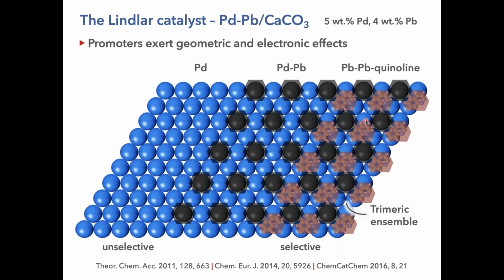Now, with this understanding of very well-defined motifs, in this case a trimeric ensemble of palladium, the design of better catalysts, that means containing much less palladium and containing no lead, could be undertaken. And it's all based on replicating this motif, this trimeric ensemble motif, in more environmentally friendly catalysts. So that's our descriptor, the ensemble size and the ensemble geometry.